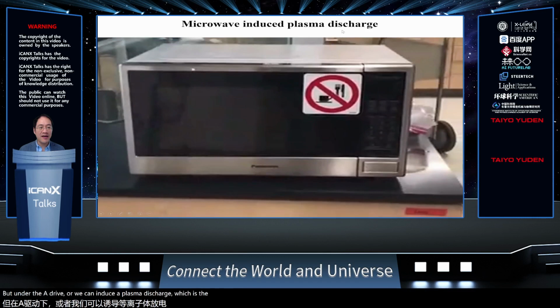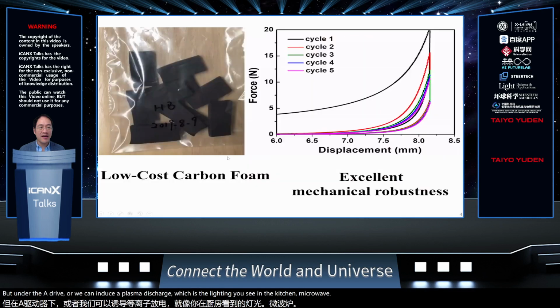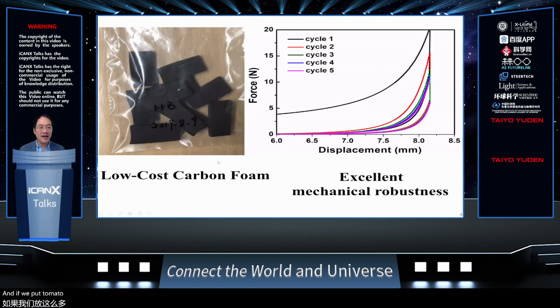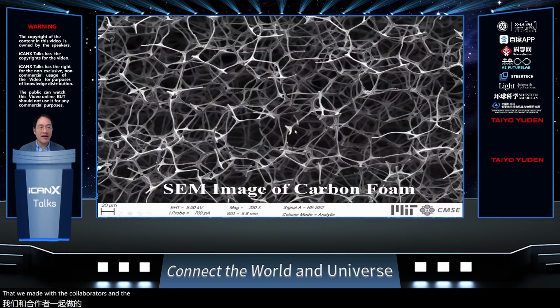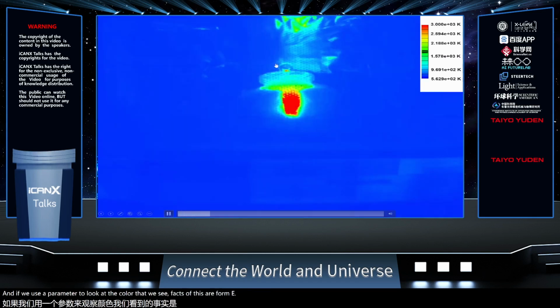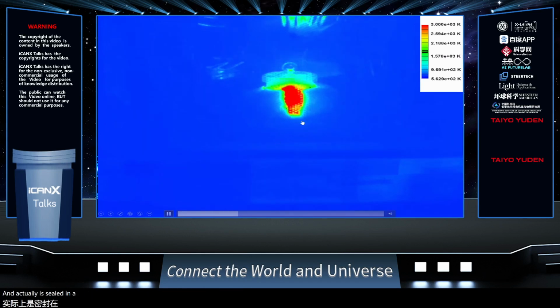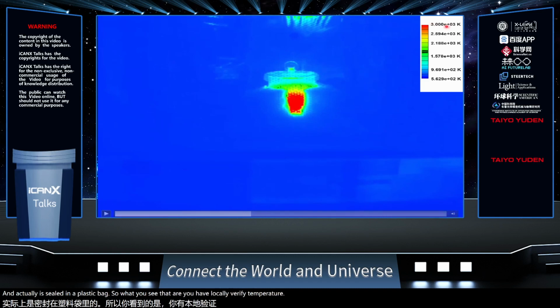So to illustrate, this is a kitchen microwave, but under the drive, we can induce a plasma discharge, which is the lighting you see in the kitchen microwave. That plasma is induced by a carbon foam that we've made with collaborators. And the foam looks like this. So under the electric field, it induces a plasma discharge. And if we use a pyrometer to look at the color, we see that this foam is in a jar, and actually it's sealed in a plastic bag. So what you see is that you have locally very high temperature, approaching 3000 Kelvin.